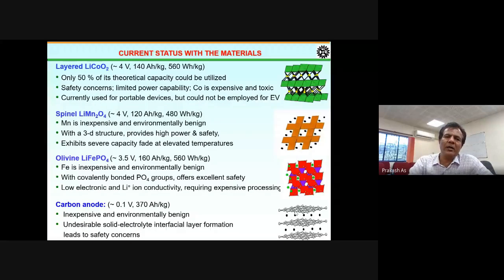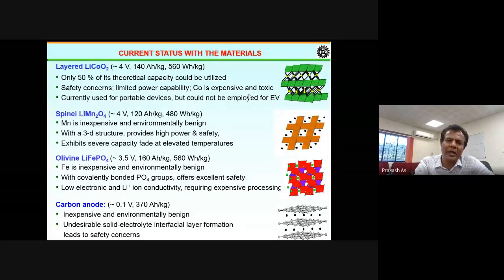You have lithium cobalt oxide, which, as I said, was the invention of Professor Goodenough. Still, this material is being used even till today, and this is a 4-volt cathode, and the capacity is 140 ampere hour per kg, and gravimetric energy density is about 560 watt hour per kg. Here, only 50% of the theoretical capacity could be utilized, because if you draw more than 50%, there is an inherent safety aspect with this lithium cobalt oxide.